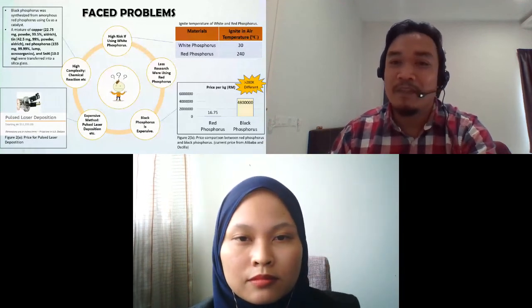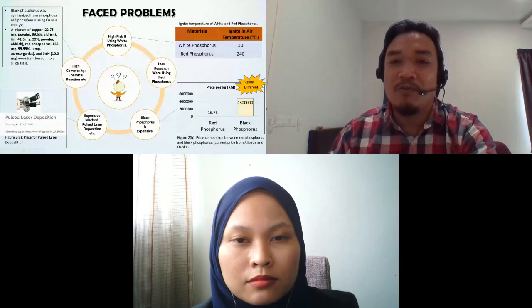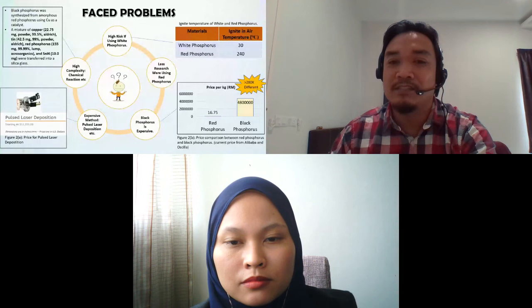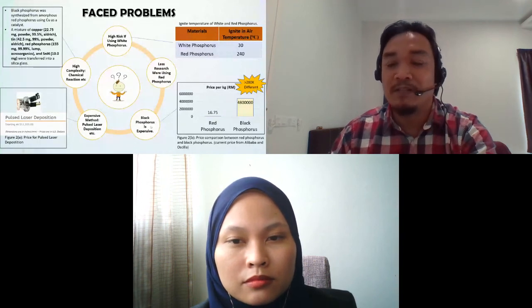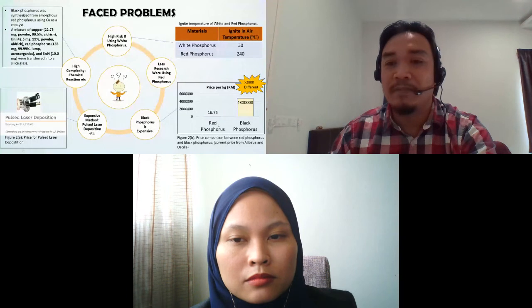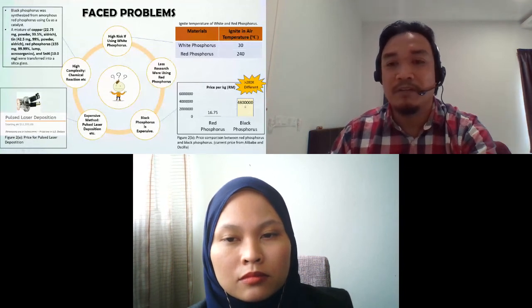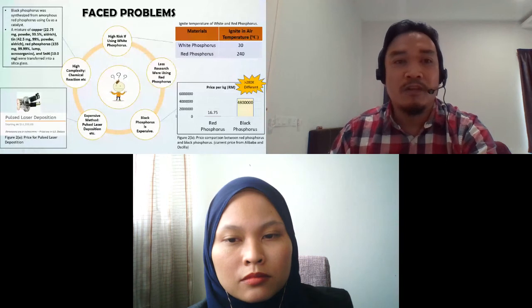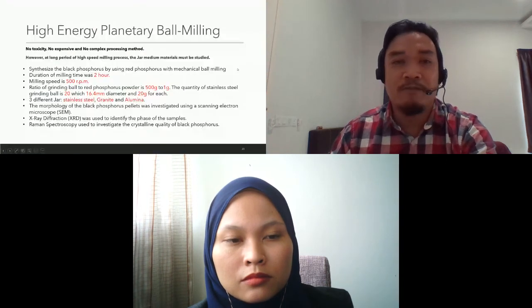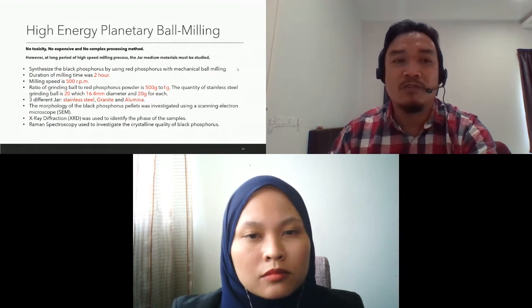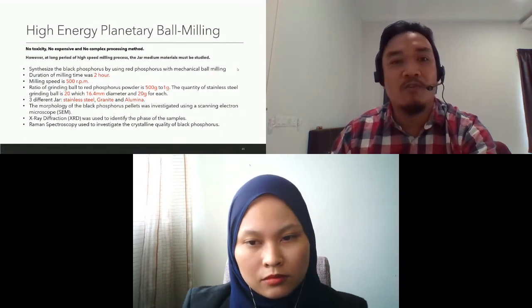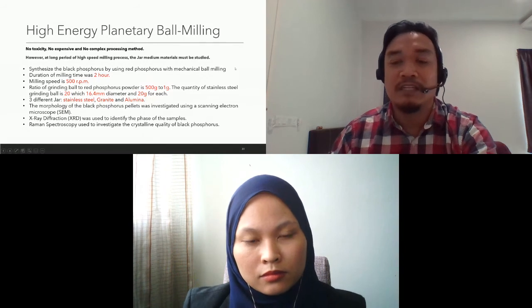And one more exciting fact is black phosphorus is expensive compared to RP. Black P is about 4.8 million RM per gram, sorry, per kilogram, compared to red phosphorus. So in order to have BP that is simple, non-toxic, not expensive, with no complex processing method, and by using RP,